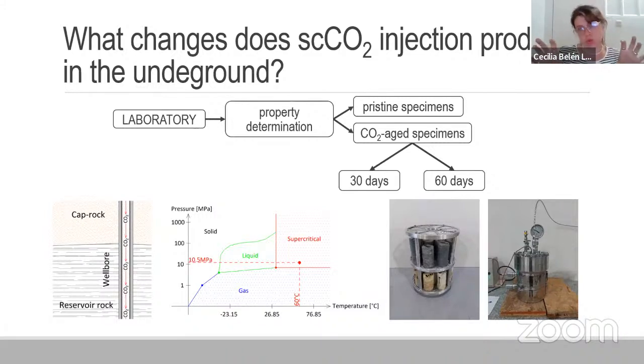The first group was the pristine specimens, which we left stored and afterwards tested. The other group we aged into two different aging periods: 30 and 60 days.